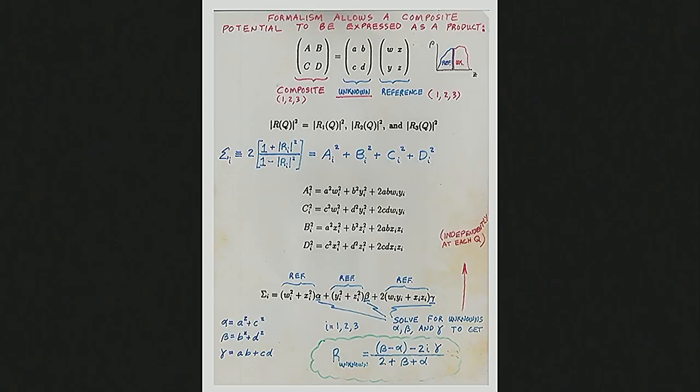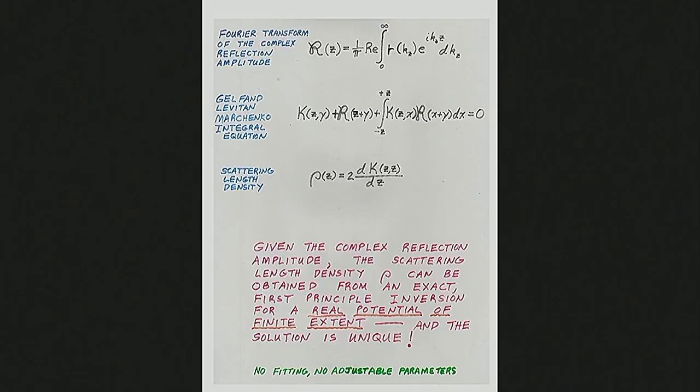So it's like holography. You actually put in some reference thing and you can get out of that the amplitudes of the actual waves. And then to invert, it turns out that a group of Russian mathematicians back in the 50s found that you can do for this very strong scattering situation a sort of more elaborate Fourier transform integral equation solution that gives you directly back, again, just as in this one-dimensional case, which is applicable for specular scattering, the solution.